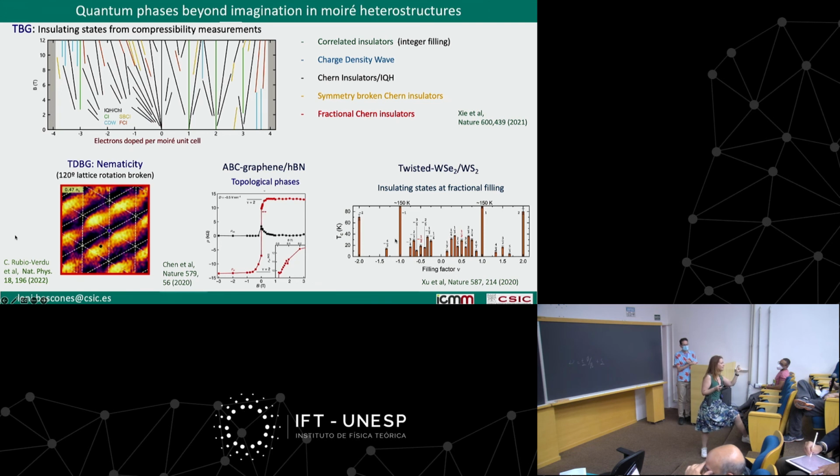So if I change slightly the parameters, like the Fermi velocity in graphene, instead of 1.1, it can be 1.08 or 1.05, or if I introduce relaxation in the system, that changes a bit. So you can write this 1.1 in terms of the Fermi velocity, the parameters of graphene, and also if there is relaxation or not.